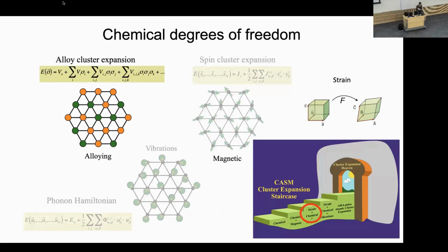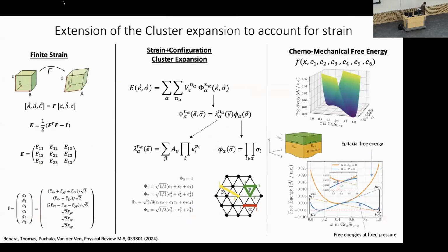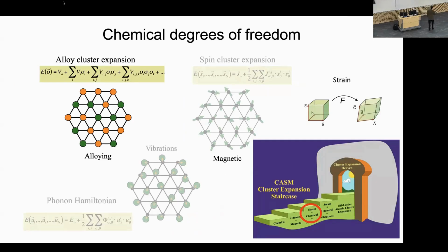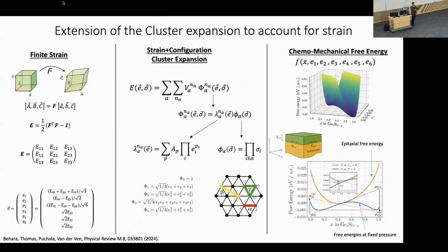Very briefly, maybe if there are any folks that grow epitaxial phases or crystals or alloys, we've extended these methods to allow for chemical degrees of freedom and strain degrees of freedom, which is important when you're epitaxially growing phases, because then the crystal that you're growing is under epitaxial strains, and that will alter all the thermodynamic properties. You can take what's otherwise a phase-separating alloy. If you grow it epitaxially, sometimes you can make it mixing or ordering, so you can drastically change the thermodynamics. And this is a very busy slide.